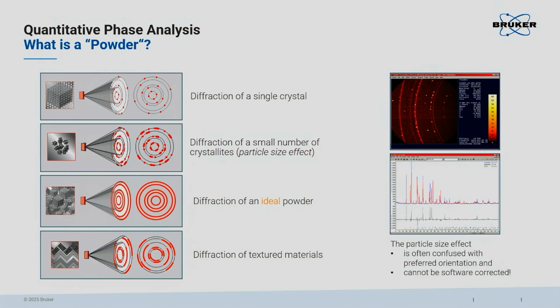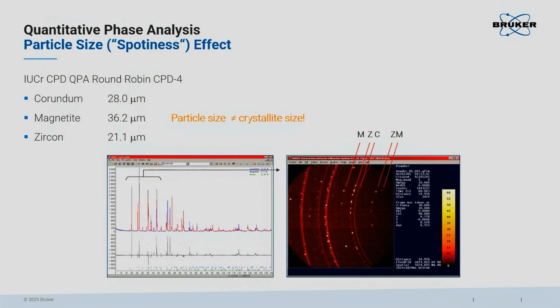In a powder pattern, you will observe the deviations like here, and I have a larger picture here. So this is a mixture of corundum, magnetite, zircon. The concentration is well known. This is one of the samples from the quantitative phase analysis round robins, which I mentioned. You will get the paper. And, at first glance, also if you look at the difference curve, it looks like preferred orientation, but it is not. If you think about the origin of preferred orientation, and if you think about crystal size, then it becomes obvious: the larger your crystallites are, the more likely also preferred orientation becomes. And a single crystal is actually the most extreme case of preferred orientation you could think of.